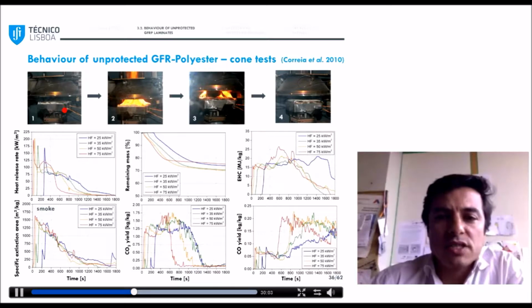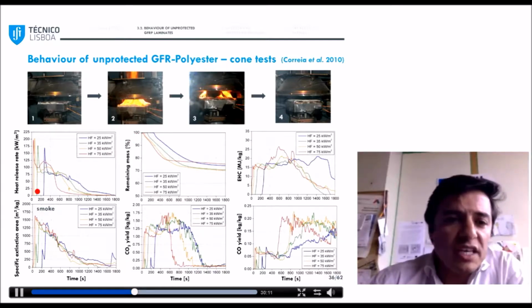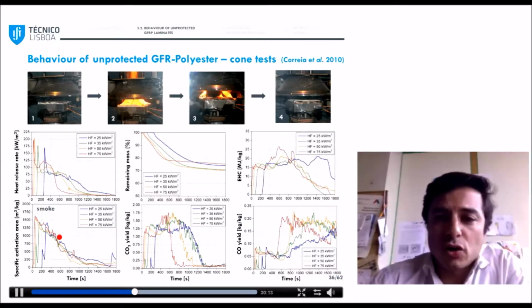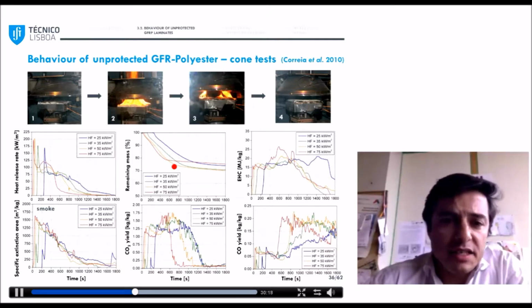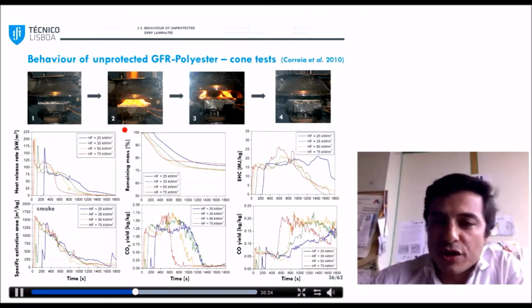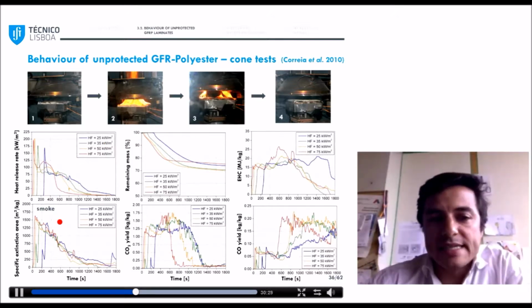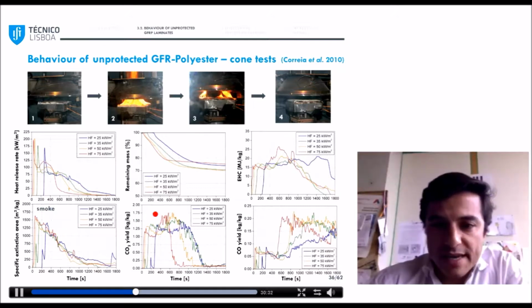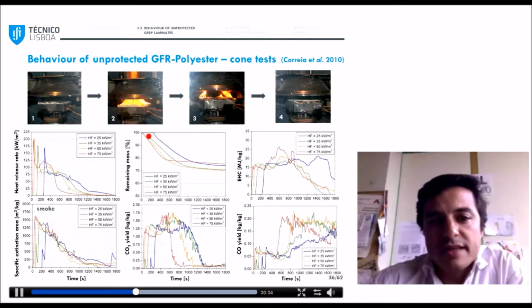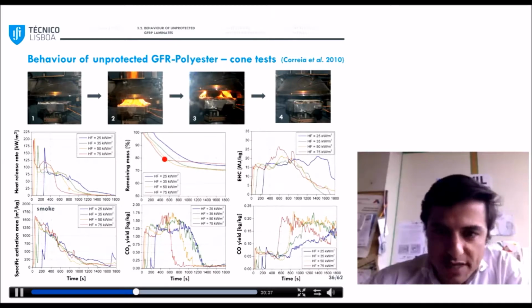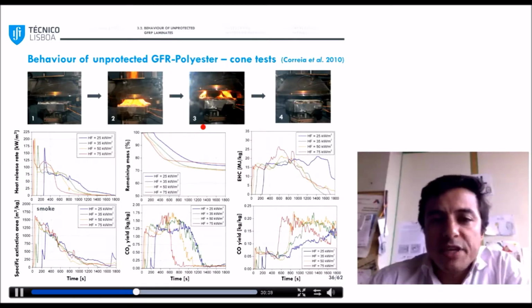So in this first stage, there are no signs of degradation. So the mass remains more or less constant, and you see no heat, smoke, or toxic gases, CO2 or CO, being released. Then, in a second stage, when the surface temperature attains a critical value, ignition occurs, the heat release rate increases almost simultaneously, as well as the release of smoke and toxic gases. And at this stage, you see that the remaining mass starts to reduce at a very high rate.